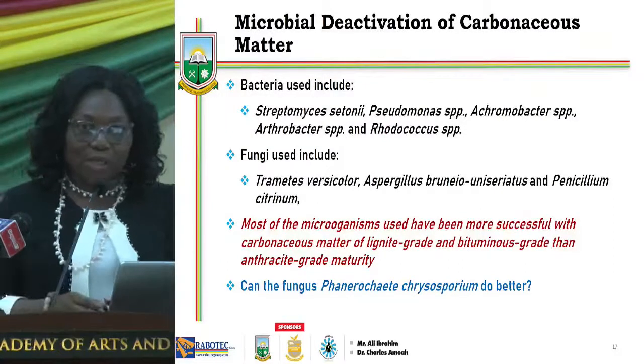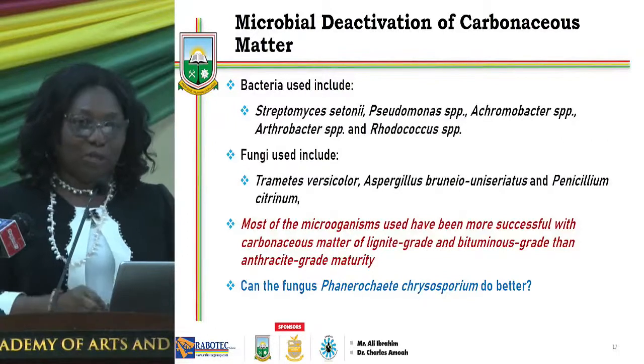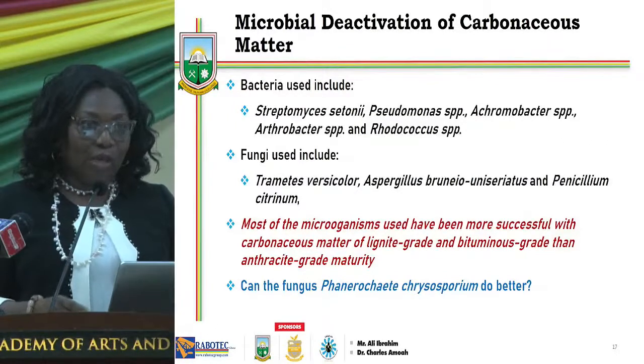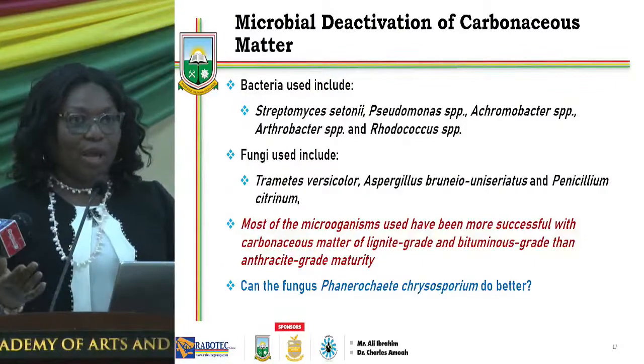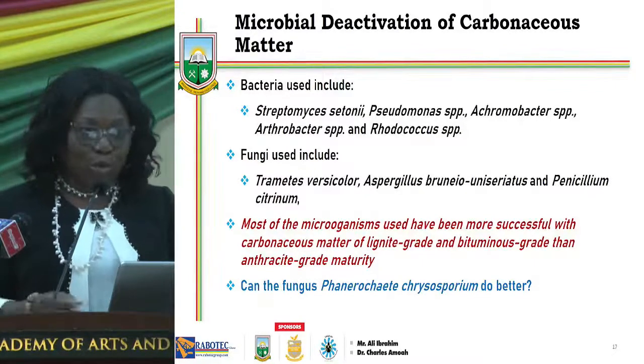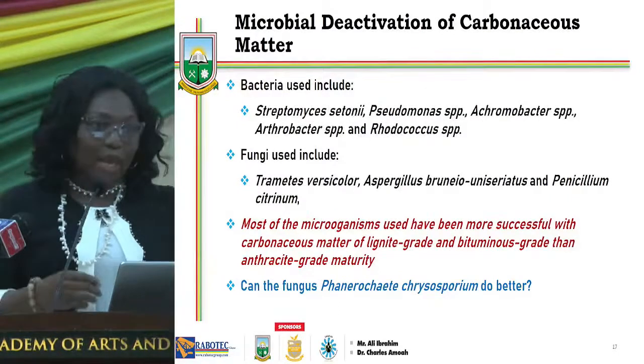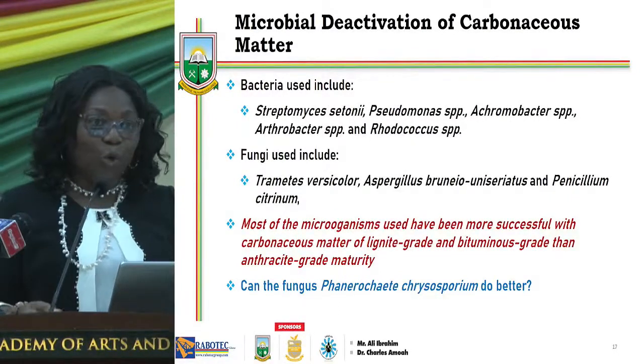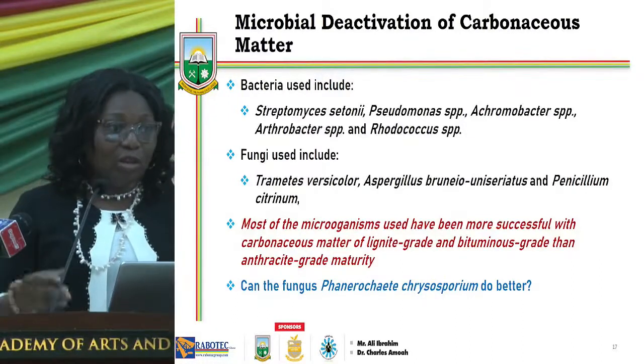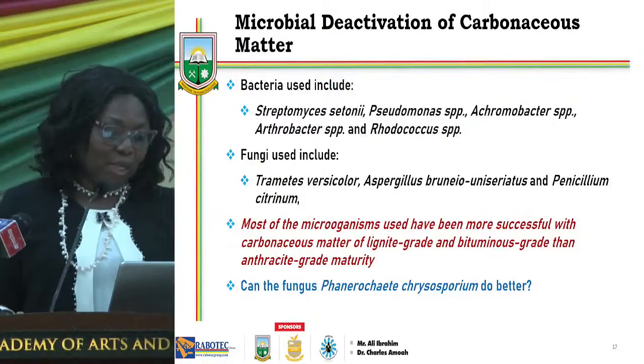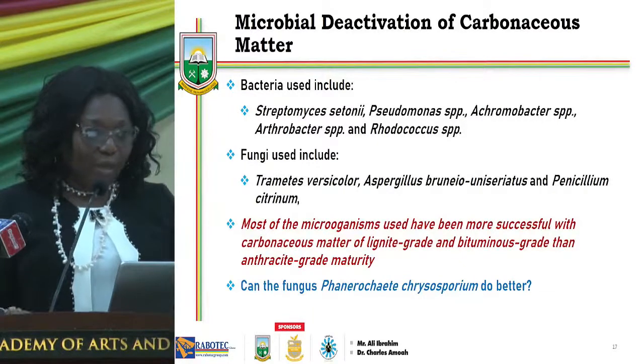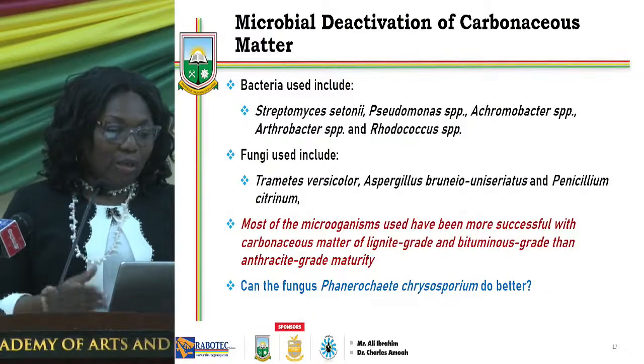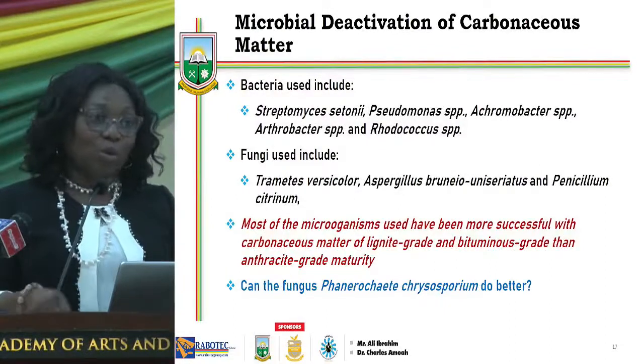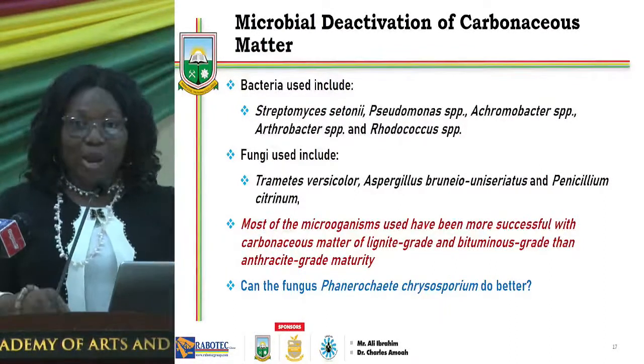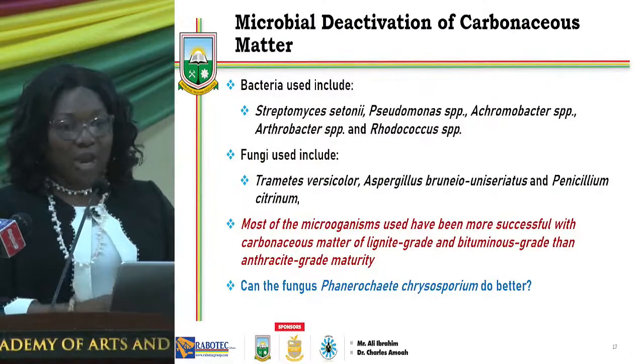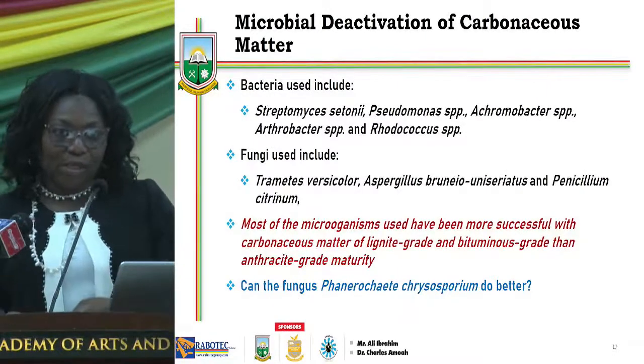Why are we interested in anthracite? The anthracite grade of carbonaceous matter, if you look through literature, consists of more than 50% of all the carbonaceous materials in gold ores. And here is the case, it can adsorb about 10 times more than the others. So there's an interest in finding ways of biotransforming anthracite. Some research has been done, but the results show that most of these microorganisms are able to degrade more of the lower rank coals rather than anthracite.